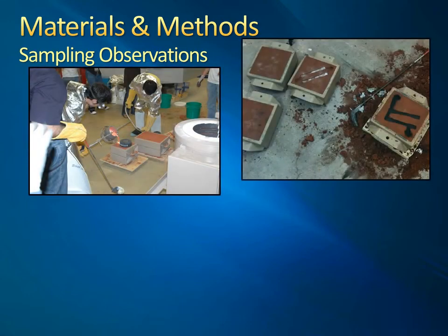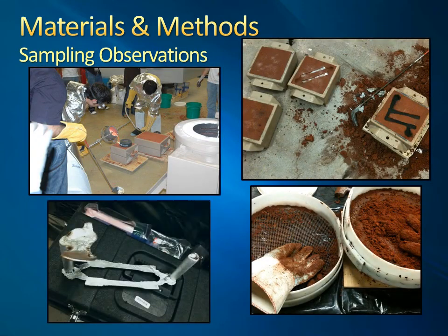The preparation of the sampling molds took much more time than anticipated. To ready the molds, the green sand, which is actually red brick in color, must be passed through a series of sieves to break down the larger compacted pieces and remove any leftover metal slag. This process, along with the mold compaction, took up to an hour per mold and required a large amount of physical exertion. The green sand was easily spread and dispersed around the area and was tracked via foot traffic.